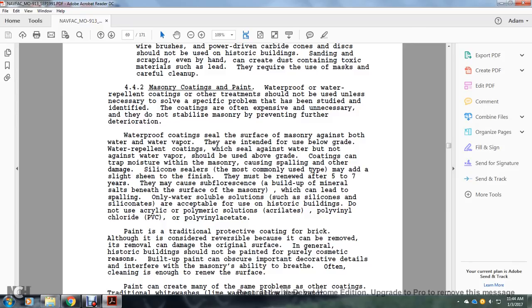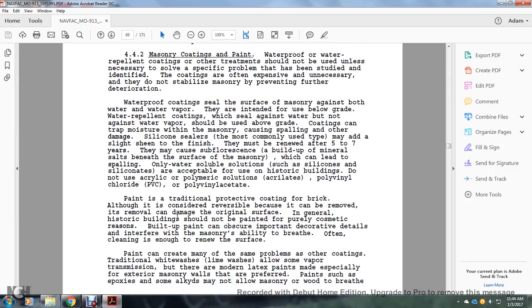Silicone sealers are the most commonly used type. They may add a slightly glossy sheen finish. They must also be renewed about every 5 to 7 years. They may cause efflorescence, or buildup of mineral salts beneath the surface of the masonry, which can lead to spalling. Only water-soluble solutions, such as silicates and siliconates, are acceptable for use on historical buildings. Do not use acrylic or polymeric solutions, acrylates, polyvinyl chlorides, or polyvinyl acetate.